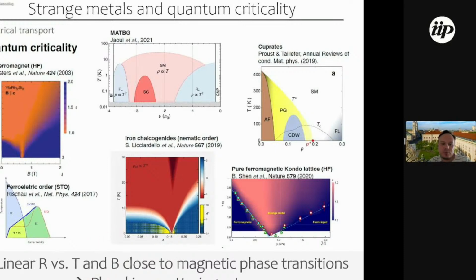And also usually one accompanying feature is that the metallic state has a Planckian scattering rate, which means that if you extract the scattering rate of the electrons from the metallic state, you find that it scatters as fast as what is allowed by Heisenberg's uncertainty principle. And therefore, even at ultra low temperatures, these materials scatter like crazy, even in the absence of any obvious scattering mechanism. So this is what we wanted to identify in our study, and we wanted to take a closer look at these strange metal phases and compare them to other materials.